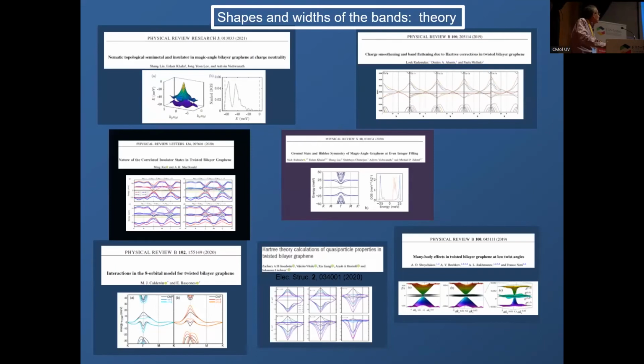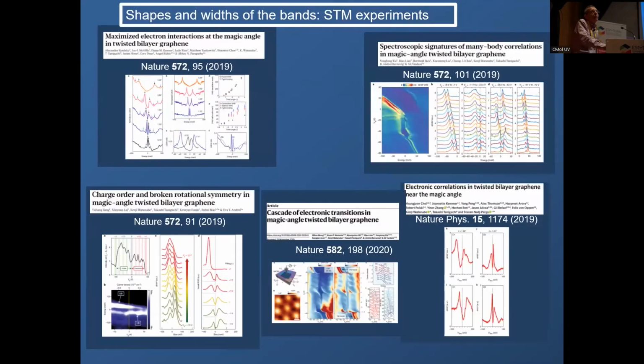And I showed to you before our calculations, and that has been confirmed by many other calculations, and more importantly by experiments. These are STM experiments performed about 1.5 to 2 years after the initial discovery of the phase diagram of twisted bilayer graphene, and all these STM experiments show peaks in the density of states. So definitely there are narrow bands, but these peaks are at least an order of magnitude wider than the bandwidth predicted by theory in the absence of interaction, which is a few meV. Typically, the bands you find in this system are no less than 30, 50 meV wide.